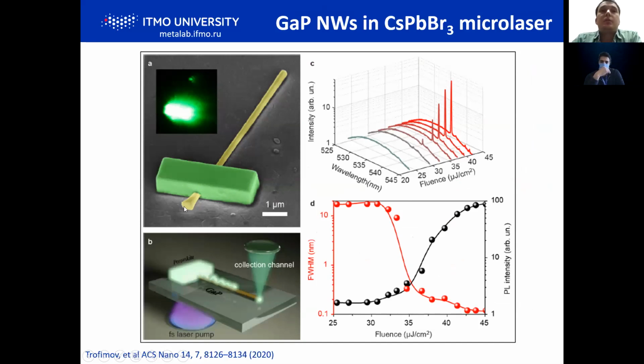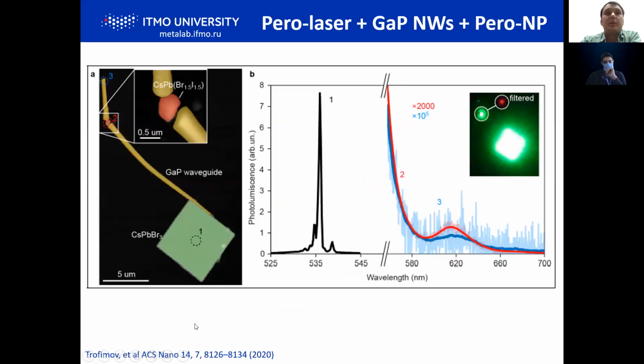We see that even if two materials are integrated into each other by such methods, just simple chemical growth of these two different materials, we still have lasing with good thresholds and we have light coupling into this waveguide. Here we see that we can integrate this waveguide with another light-emitting nanoparticle made of another, reddish perovskite, and also we can couple it with another waveguide. You see the result: by initiating lasing here, we can initiate photoluminescence after waveguiding and pump this nanoparticle, it emits a red line, and then some part of the light decouples at the end of this third facet.